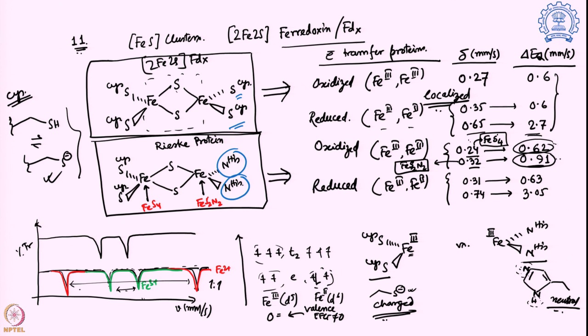Because we are talking about a FeS2N2 system, much more asymmetric compared to FeS4, relatively symmetric. So as you induce more asymmetry in the coordination geometry, this is actually getting further split. And that is going to continue even in the reduced state, where it is the C2 signature.